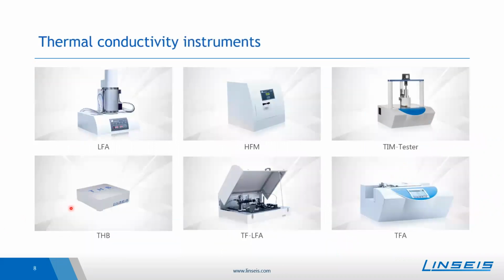LINSEIS offers a broad range of thermal conductivity instruments. The heat flow meter, shortly HFM, and the thermal interface material tester both belong to the steady state methods. So these are both plate methods where one has two plates. One of them is cooled and the other one is heated, and a sample is sandwiched in between. And then one waits until the applied temperature gradient leads to a constant heat flow through the sample. All of these other methods are transient measurement methods.